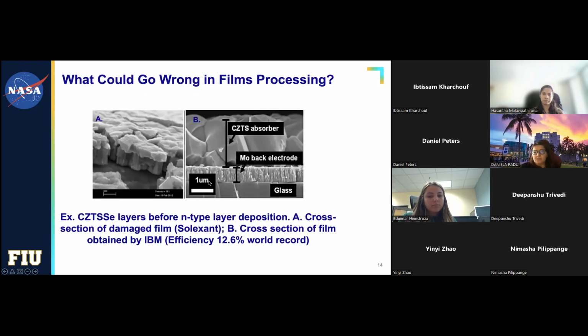And there are some caveats in this film processing, because if I have a very good process, and this is where the frustration comes, especially in graduate school, right? If you are working to get your solar cell done and you don't take care of your process, this is what happens. I'm going to take advantage of the fact that this audience is quite savvy in electrical engineering. Here you have a shunt, so you're going to have a short immediately, because you're going to touch the top conductor with the bottom conductor if your layer is not nice, smooth and uniform, right? So this is not a success story.